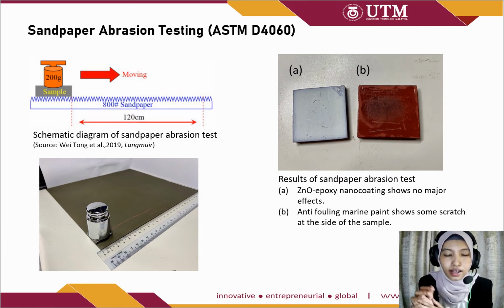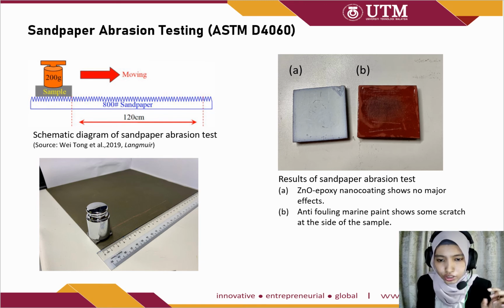Okay, next, I did sandpaper abrasion testing with ASTM D4060, where in the photo shown the sandpaper has a grade of 800 grit, sorry, and there will be weight on the sample and it will move constantly. So here's the result of the sandpaper abrasion test. The zinc oxide epoxy nanocoating shows no major effect, while the antifouling marine paint shows some scratches at the side of the sample.